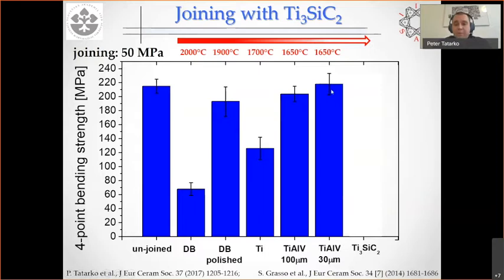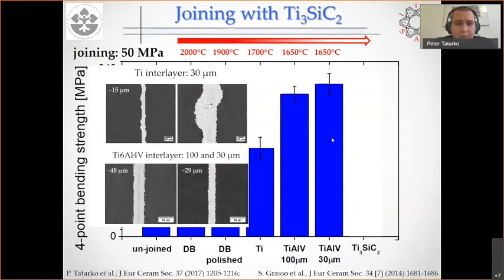These results were very positive, and we were very happy about that. Unfortunately, when we look at the cross sections of these joints, there were two important issues we found. The first was a significant shrinkage of the filler. Here you can see we used a titanium interlayer with a thickness of 30 micrometers, and we ended up with the interlayer about 15 microns.